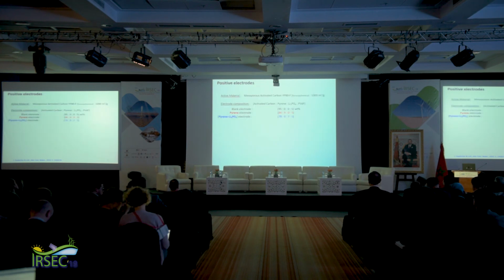Okay, so to summarize, we are using pyrene as an electron donor additive. We are using lithium phosphate as a lithium-ion additive, and we expect to have a cascade type mechanism. I mean, as soon as the protons are released by the oxidation of pyrene, they should be captured by this acid-base reaction, which will release lithium ions. So this is what we expect.